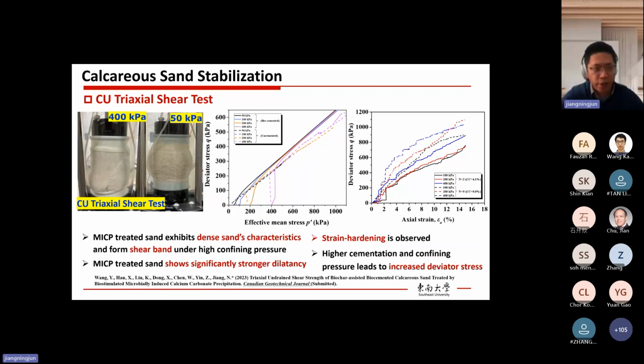And also by measuring the change in the soil volume, we find that the bio-cemented sample shows stronger dilatancy compared with untreated samples. Then from the deviator stress versus axial strain curve, we find that firstly, it exhibits a strain hardening trend. Secondly, with increased cementation level, here the solid line shows the 4% cementation, and the dotted line shows 9% cementation. Compared with the solid line, the dotted line definitely is higher, right?